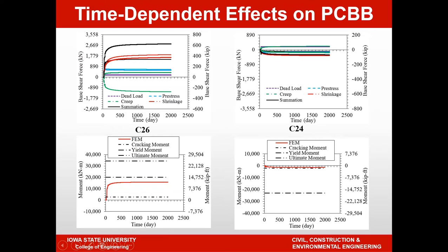At the bottom you see the corresponding moment, and on top of the corresponding moment, I've also shown the cracking moment, the yield moment, and the ultimate moment. If you look at column C26, in this case you can see that the moment buildup is getting very large and getting closer to the yield moment, whereas in column C24, the buildup of moment is small enough that you're not even expecting the column to experience any flexural cracking.